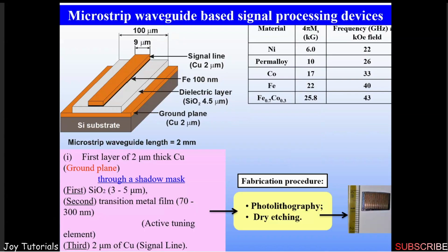Now, what we do here is microstrip waveguide based signal processing devices. There is a microstrip line on a silicon substrate. Then we deposit a ground plane of copper, then we have a dielectric through which the electromagnetic wave will propagate. It is silicon dioxide, 4.5 microns. On top of this is the tuning material, an iron film for example, 100 nanometers. On top of this is the signal line again. So between these two conducting layers, there is a copper layer at the bottom and a copper layer at the top. The electromagnetic wave will propagate from port 1 to port 2.